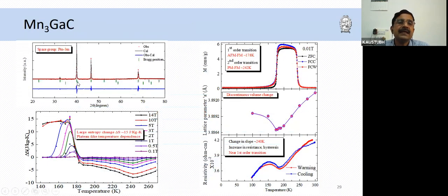So here are some characterization results on manganese-3 gallium carbon. This is the XRD. It is cubic with space group Pm-3m. Then you can see the magnetization data. There is a paramagnetic to ferromagnetic transition at around 240 Kelvin, and then it drops to an antiferromagnet at around 175